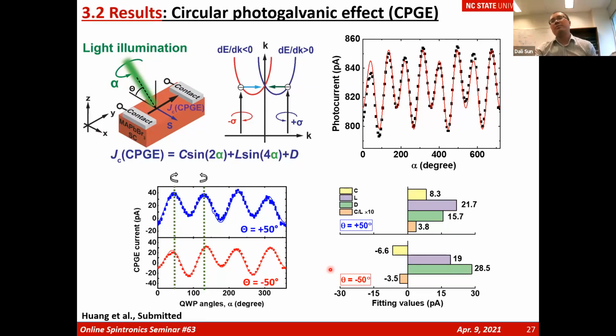The calculation can be seen here in the gray area. The L component, which is a linear photogalvanic component, is not really spin dependent, always positive. If we reverse the incident angle from positive to negative, we see the C component, the circularly photogalvanic component, reverse sign as direct evidence of the spin-splitting state in such surface hybrid perovskite materials.